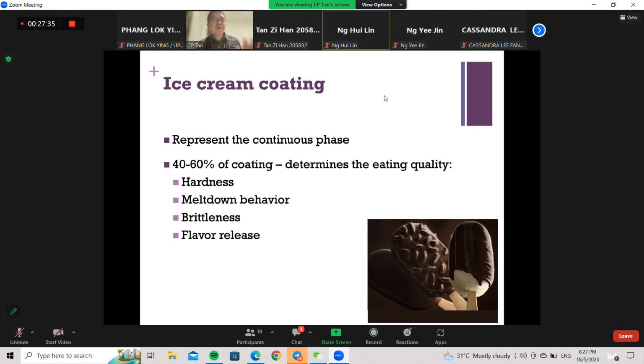Yeah. And if you buy a cheaper non-Magnum coated ice cream, sometimes you notice that the coating is a very thin layer, and sometimes at the edge, the one closer to the wooden stick, where my cursor is now, a certain part of the ice cream mass is not fully covered by the coating. Have you observed that kind of defect in coated ice cream when you buy cheaper versions?